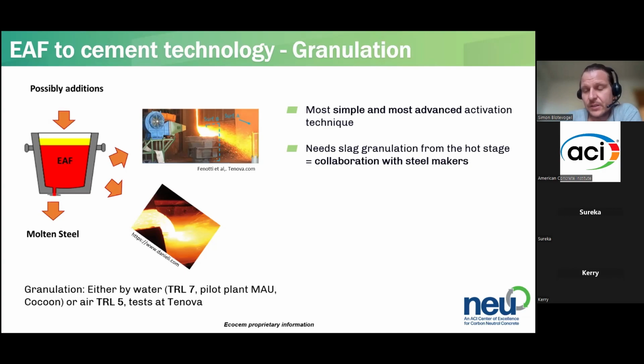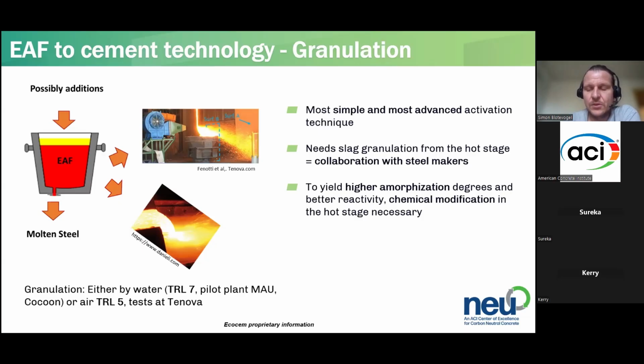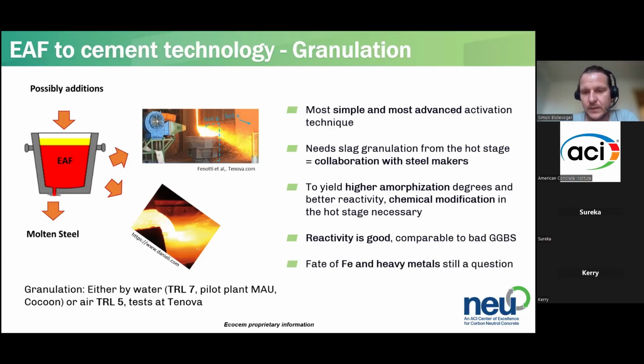However, to granulate the slag, you need to have it in the molten stage. So it needs some sort of cooperation with the steel makers, because you don't want to remelt the slag at some other place, because it would be very intense in energy and costs. Usually for EAF slag, to have high amorphization degrees and better reactivity, we'll get to that, some sort of chemical modification is necessary. Usually you need to increase the amount of network formers, glass network formers in the slag. The reactivity that you get out from quenching trials is usually good, about a bad blast furnace slag, I would say.